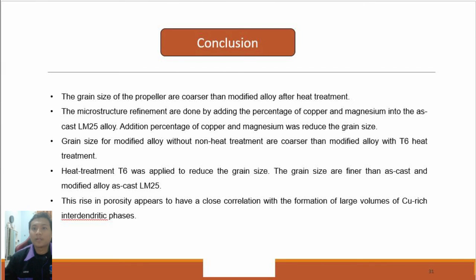For conclusion, the grain size of the propeller is coarser than the modified alloy after heat treatment. The microstructure refinement is done by adding percentages of copper and magnesium into the as-cast LM25 alloy. The addition of copper and magnesium reduced the grain size. Grain size for the modified alloy with non-heat treatment is coarser than the modified alloy with T6 heat treatment. Heat treatment T6 was applied to reduce the grain size. The grain size is finer than as-cast and the modified alloy as-cast LM25. This rise in porosity appears to have a close correlation with the formation of a large volume of copper-rich interdendritic phase.